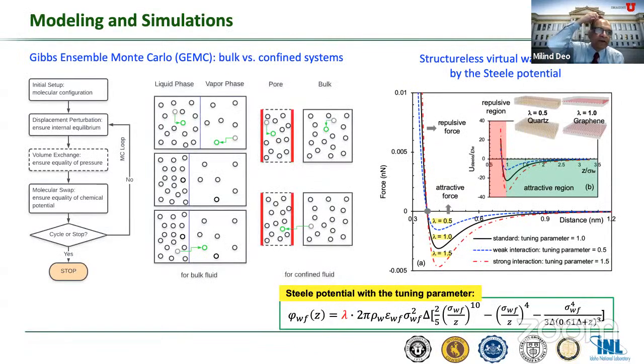And then we were able to use Gibbs ensemble Monte Carlo simulations. These were initiated by one of my former PhDs, Manas Pathak, but then they were taken over by Idaho National Lab. We have to use some type of virtual wall interaction parameter lambda that defines the interaction between the wall and the fluid, and that then determines whether the boiling transition in this case happens before or after the bulk transition.